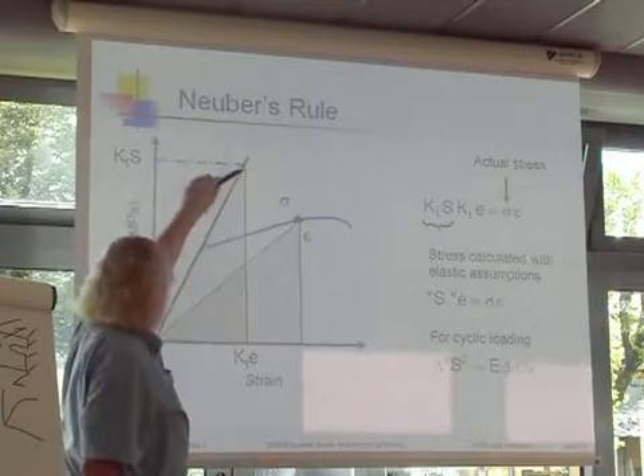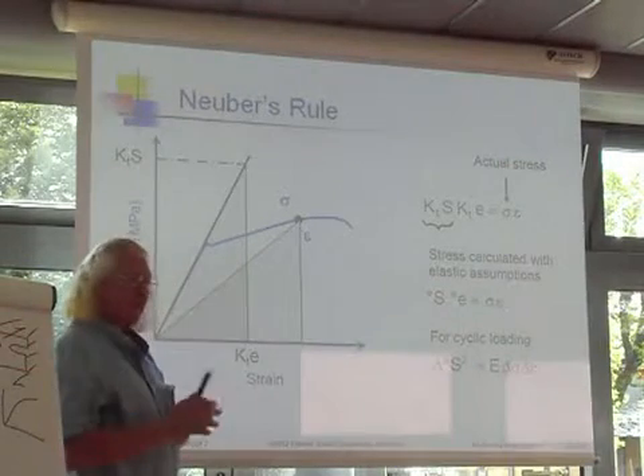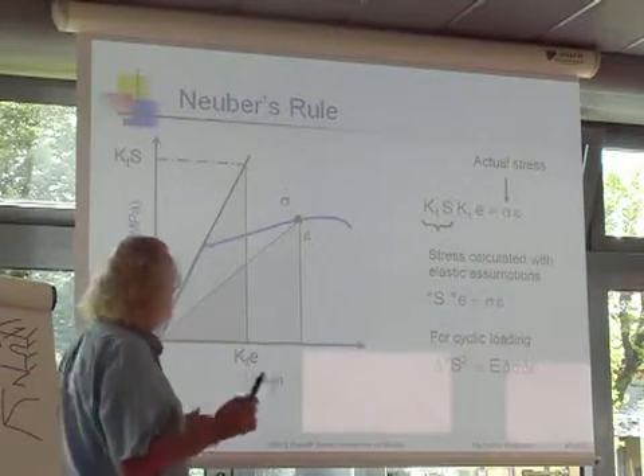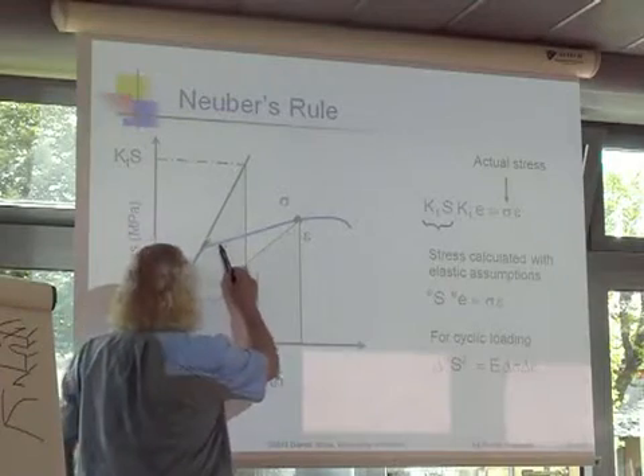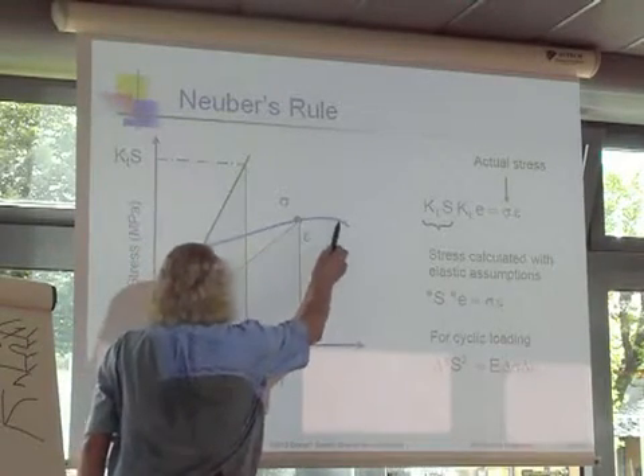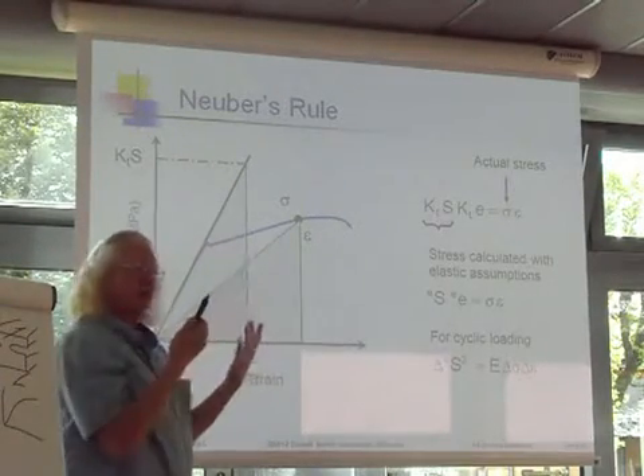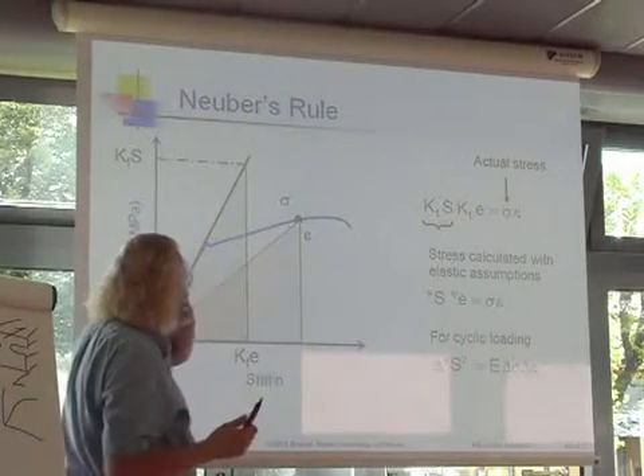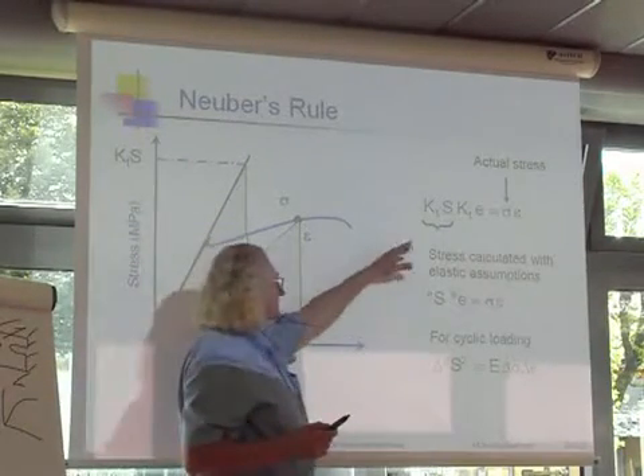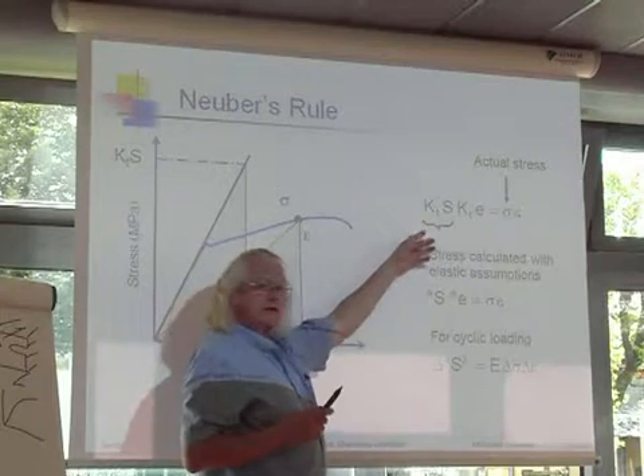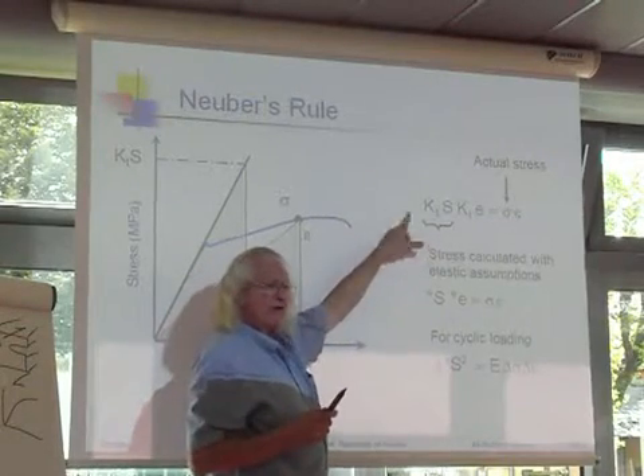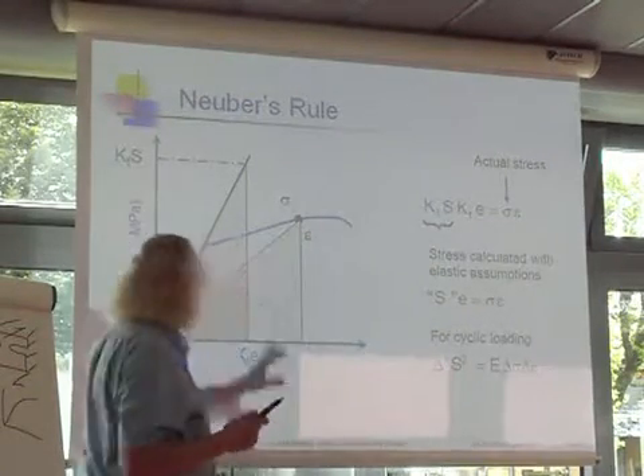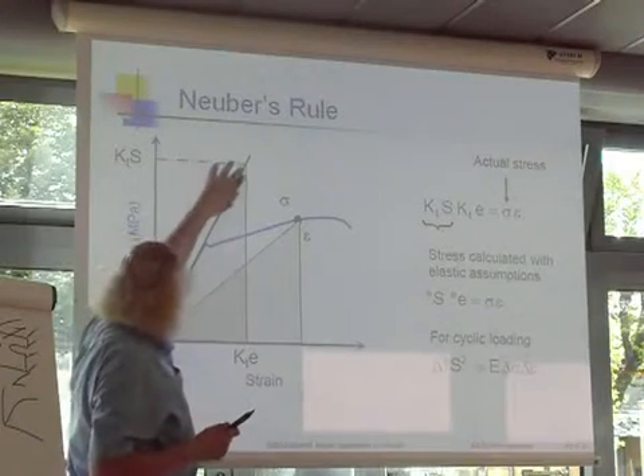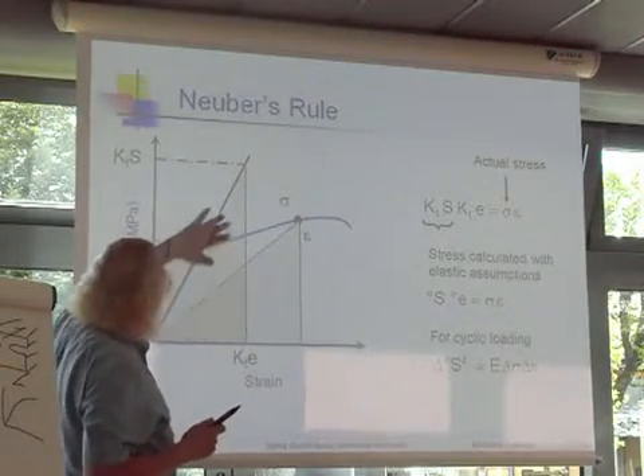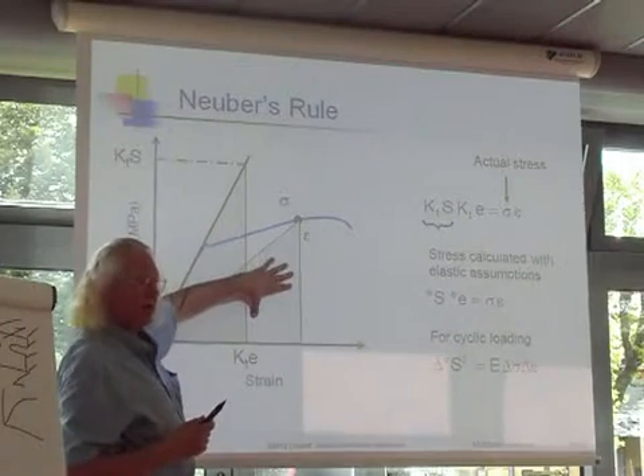And so I've calculated the solution here elastically. And of course I know the real solution must lie somewhere along this curve, because that's the real material response. And where does it lie along that curve? Well, if you look at this, this is essentially an energy argument, because if I put 1/2 out in front of both sides, I get the energy. So you can essentially say that this area, right, is equal to this area.